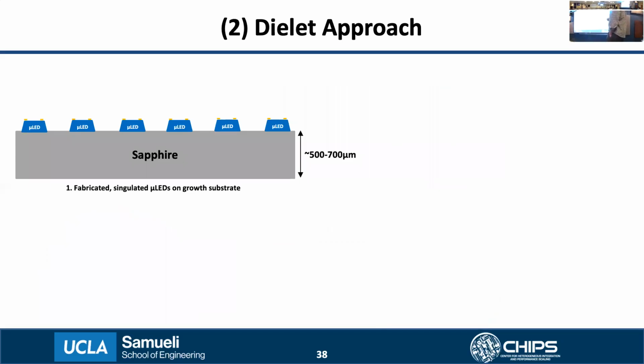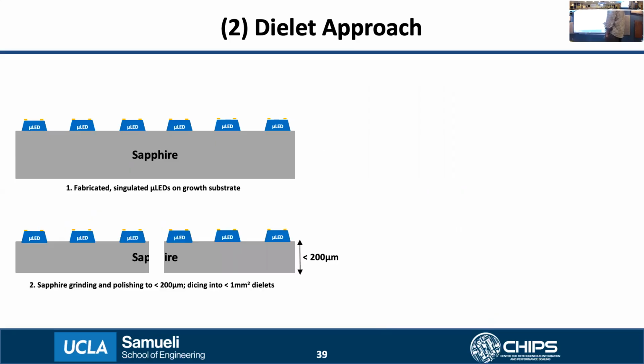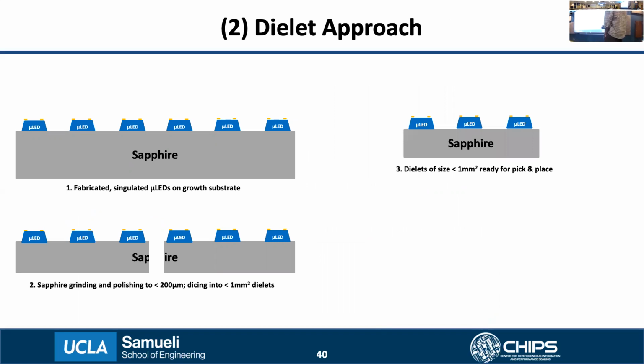So next, let's see how the dielet approach is done. In the dielet approach, we take a standard thickness sapphire wafer, around 500 to 700 microns thick, with singulated micro LEDs on it. Then we thin down the sapphire substrate to less than 200 microns thickness, and dice it into sapphire dielets of less than 1 millimeter square with micro LEDs on them. Once we have these individual sapphire dielets in step 3, we can do pick and place for assembly onto the flex strip.